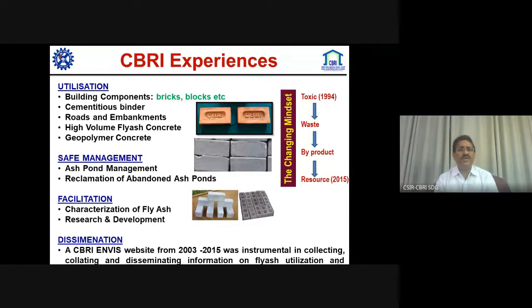More than three to four decades back, the Central Building Research Institute started working not only on cement-based fly ash bricks, but also on burnt clay bricks. We started mixing fly ash into the soil and making burnt clay bricks, and also stabilizing the fly ash with a cementitious binder varying from 7.5% to 10%, and different types of bricks were made with fly ash. At that time CBRI also developed fly ash brick making machines, etc.